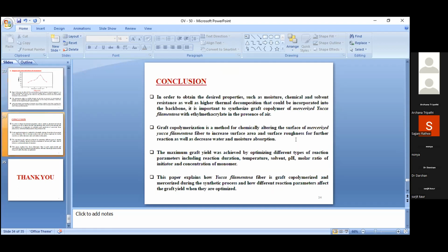Conclusion. In order to obtain the desired properties such as moisture, chemical and solvent resistance, as well as higher thermal decomposition that could be incorporated into the backbone, it is important to synthesize graft copolymer of mercerized Yucca filamentosa with ethyl methacrylate in the presence of air. Graft copolymerization is done on mercerized Yucca filamentosa fiber to increase surface area and for further reaction, as well as to decrease water and moisture absorption.